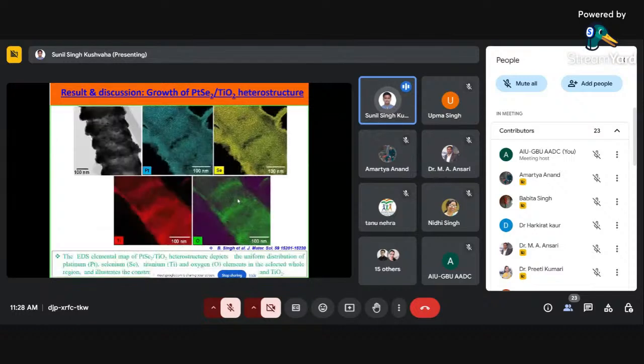And same thing during this TEM measurement, we also done this elemental mapping. So this is again our PtSe2 coated TiO2. Here you can see when we have the Pt, of course Pt is also here, and then Pt is also here, and then selenium is there. But when we are coming to the titanium TiO2, we can just see, because this is the Pt, this is the Pt, but here there is no Pt, because we are mapping only titanium. So it means this is the reduced size compared to this one. The same thing for the oxygen. So it clearly showed, okay, whatever you have grown, it is covering outside the TiO2 nanotube. It is not going inside the nanotube. And then accordingly, even we can estimate what is the thickness of the PtSe2.